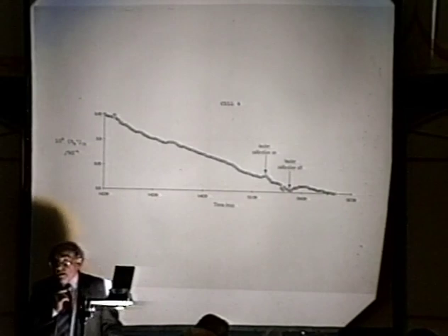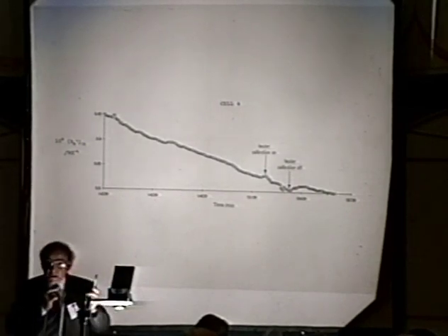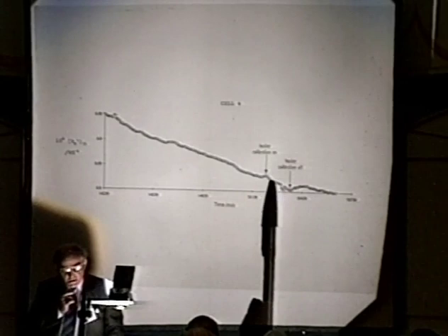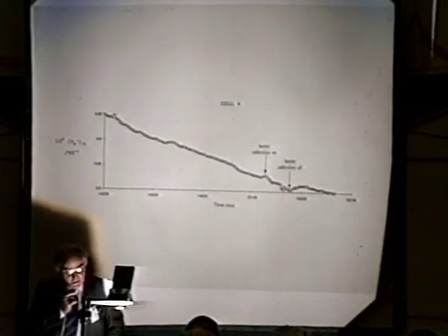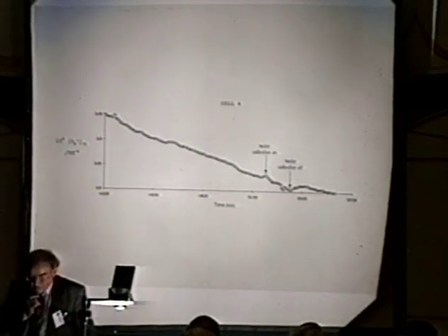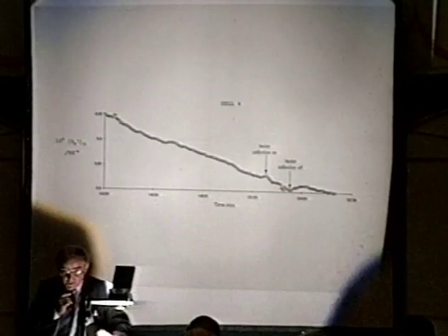This is really a reflection of the sort of tidal effect which Wolf Hansen was mentioning. There's nothing unduly untoward in applying the heater calibration. It doesn't allow for the heater power in, the heater power off. We get this decrease. We get quite a substantial, about 15% decrease. That's very important, to get a 15% decrease. Now that's about what we would expect for this cell. Wolf has already shown you.